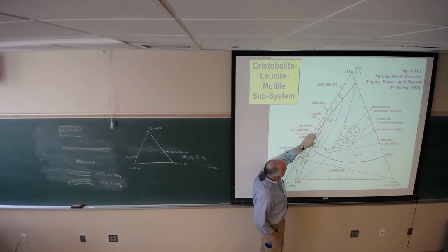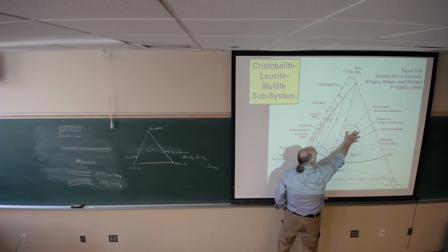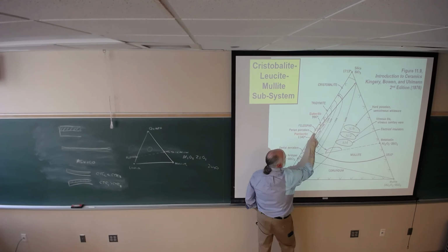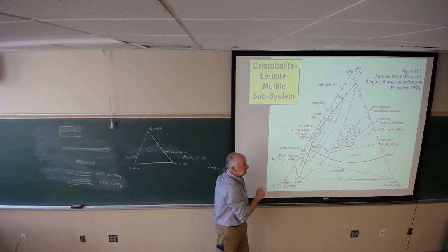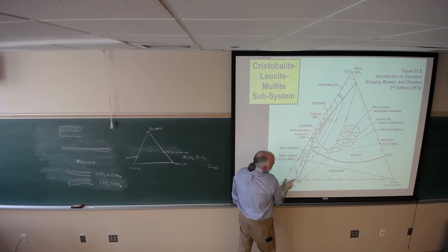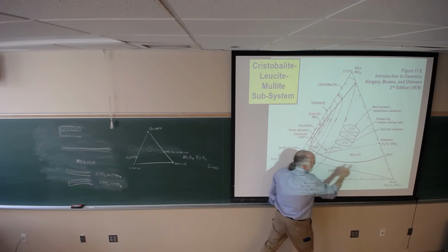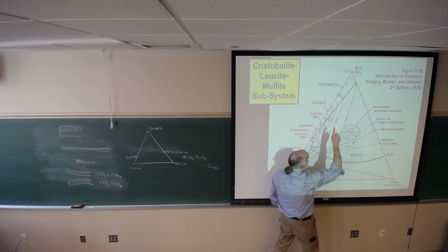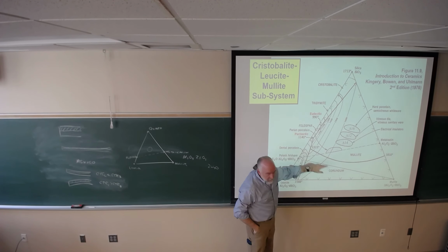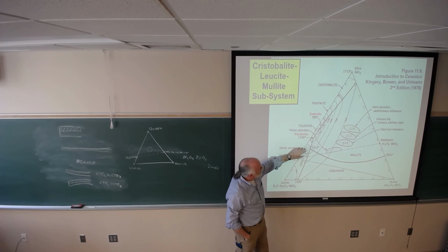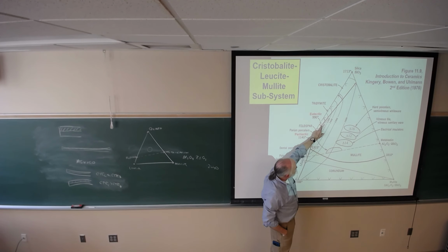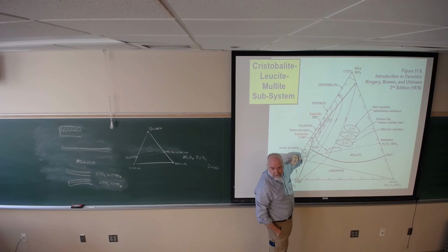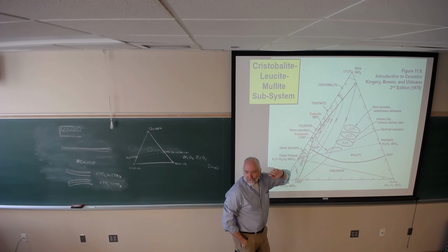So you have, this is the mullite phase field, this is silica, this is a sliver of the feldspar phase field, this is the leucite phase field here. So I have feldspar here, I have mullite down there, I have silica up there. This composition triangle, or phase triangle, right? The intersection of the three phase fields lies within that triangle. It's a eutectic. Don't worry, we're going to talk about this again, okay?